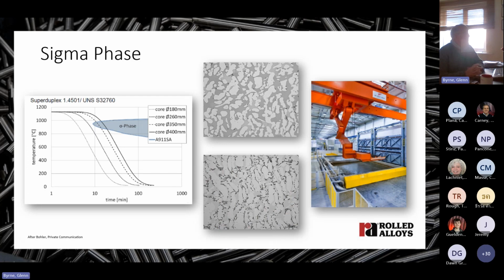So let's talk a little bit more about sigma phase. The graph on the left shows the time and temperature ranges where sigma forms. That's this phase field here. So we solution heat treat super duplex stainless steels at about 1100 centigrade to homogenize the steel composition and to get the 50-50 phase balance that we seek. And then we quench it as quickly as we can into water so that we freeze in the desired microstructure.